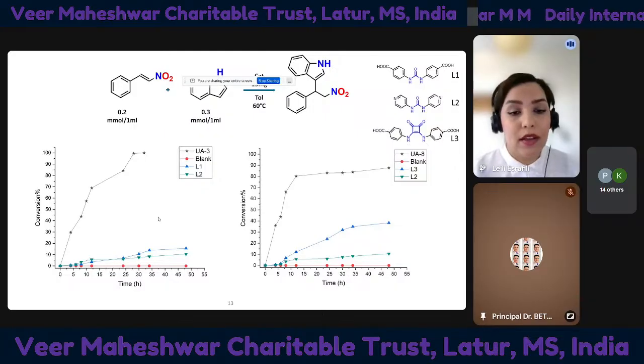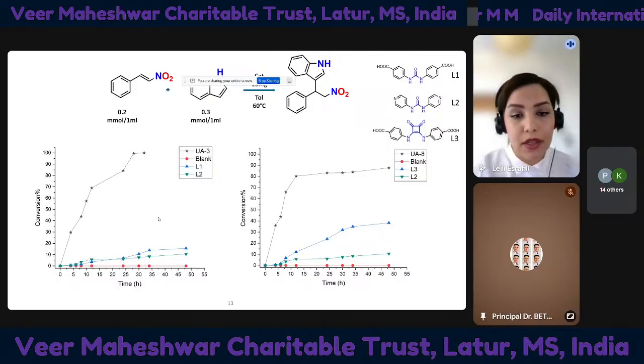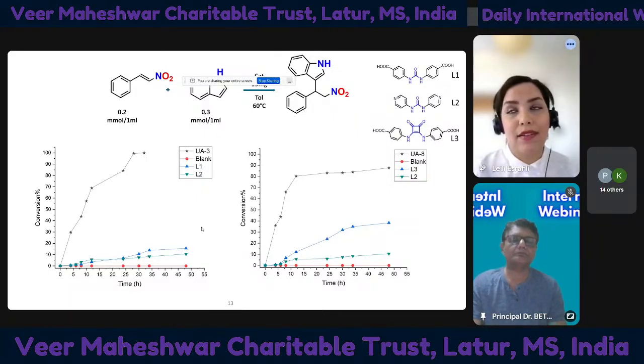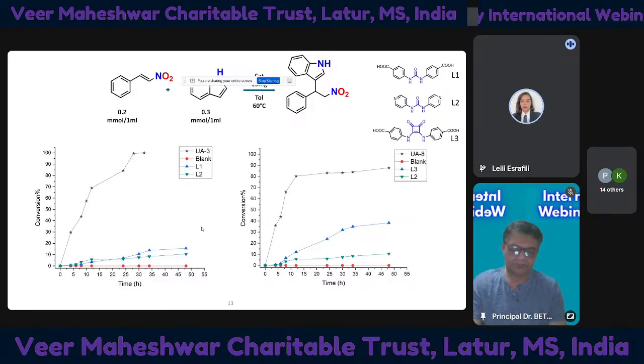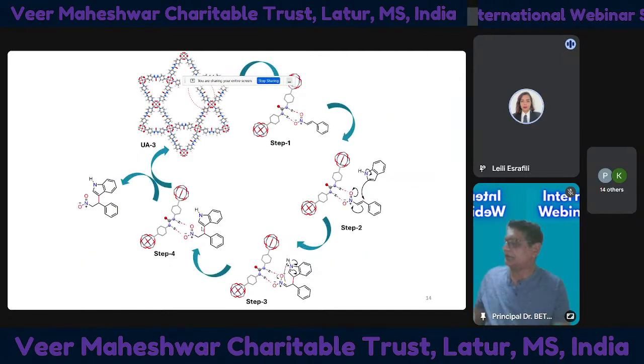This improvement arises from substrate pre-organization inside pores, cooperative hydrogen bonding, confinement effect, and improved reactant diffusion because of the larger surface area. The framework essentially behaves like a hydrogen-bonding enzyme mimic. But I also want to quickly take a look at the catalytic mechanism here, what happens mechanistically inside the MOF.